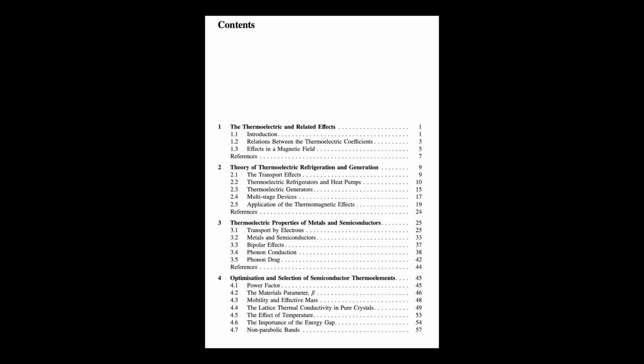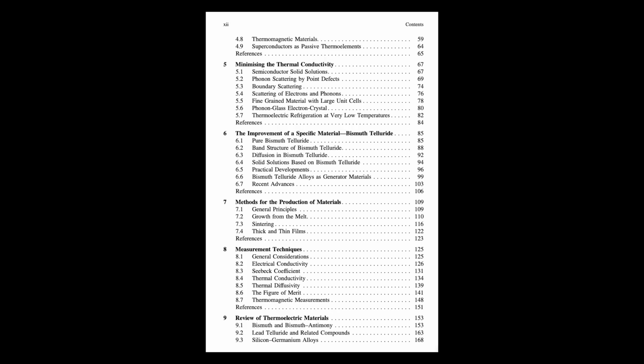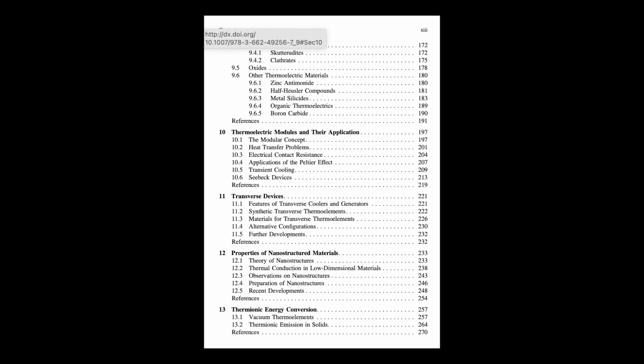Okay, avoid supercooling. What about sintering? That's powder-based. Yeah, sintering is very common for things like SiGe, PbTe, even Bi-Te alloys. You start with fine powders of your materials, press them into the shape you want. Then you heat this green compact to a high temperature, but below melting. Atoms diffuse across the particle surfaces, bonding them together, making the whole thing dense and strong. For materials like Bi-Te alloys where crystal orientation matters, you need to control grain alignment during pressing and heating, often followed by annealing, a heat treatment to homogenize things and relieve stress.